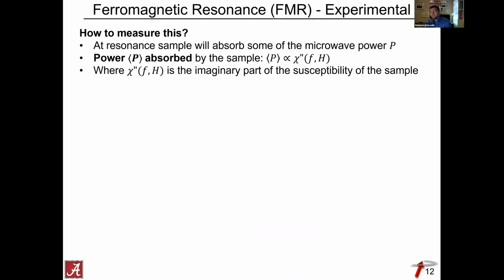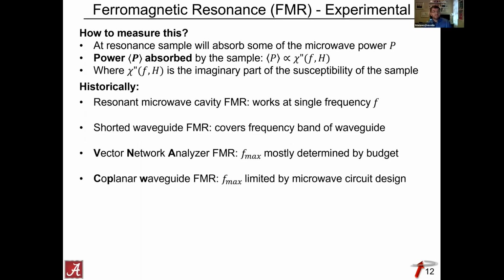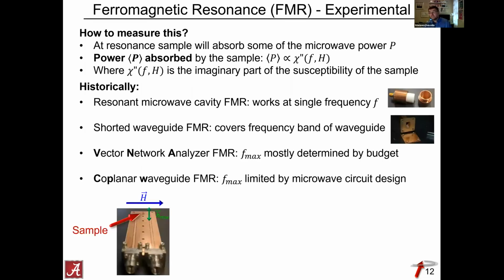Well, at resonance, when you drive the system at resonance, the system will absorb some of the microwave power that you supply. The average power absorbed by the sample is proportional to the imaginary part of the susceptibility of the sample. And so you can now essentially take advantage of that. All you have to do is measure the average power that is absorbed by the sample. And over the years, people have done that in slightly different ways.